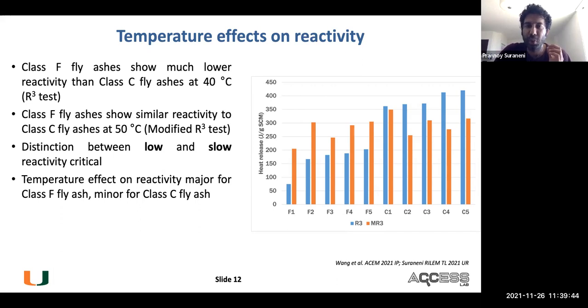But for materials which show slow reactivity, you may want to be very careful with the test or extend it for longer durations, because the class F fly ashes are actually great materials. They're super important in concrete. They give you great durability, but not at 28 days. It takes a bit longer for that reactivity to manifest. And testing them at 40 degrees might not be enough, especially if the test duration is 3 or 7 days. If you test them for longer, you're probably okay.